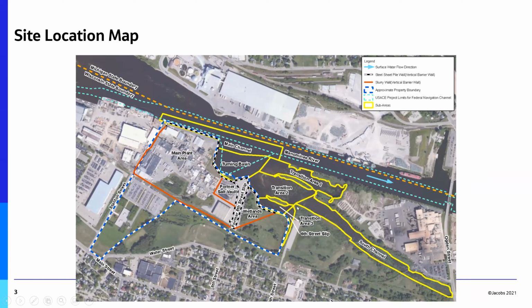So the main issue here with a dense aqueous solution is you don't know where this is going to upwell. And so you can almost think about the preferential flow paths being like blood veins, for instance. And so the challenge with this project was essentially that you could move 5 feet over and you would go from basically clean, from an arsenic perspective, to screaming hot with arsenic. And so the variability of the sediments that you would be pulling up and putting into the scow bucket by bucket load was tremendous.